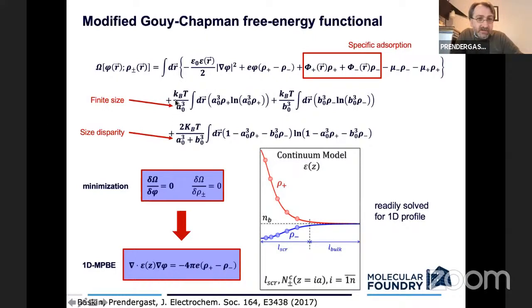These corrections here are basically entropy terms. They have this kind of a cubed rho log a cubed rho that you might remember from statistical mechanics. Those terms are related to the finite size of the object, so they place limits on the concentration as you get close to the interface. And then there's also a correction we've derived when you have a size disparity. Your cation and your anion may not always be the same size, and so A0 here refers to one of the species, the cation, and B0, the other, the anion.